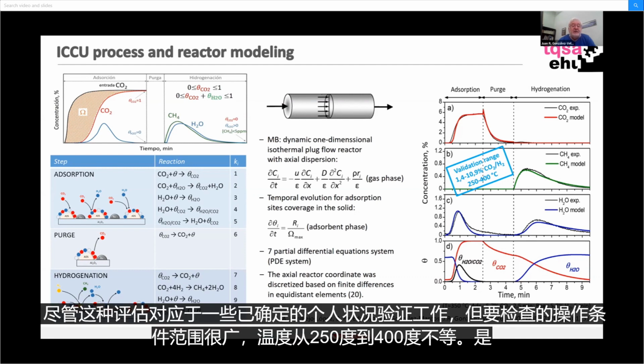Solving the system of partial differential equations by finite differences returns the evolution of the concentration of CO2, methane, and water, which are represented in the figure on the right in color lines, together with the experimental data in black lines. The chart below corresponds to the covering factors of CO2, water, and unstable bicarbonates for the last zone of the reactor. Although this assessment corresponds to some determined operational condition, validation was checked for an extended range of operational conditions, temperature from 250 to 400 degrees C.